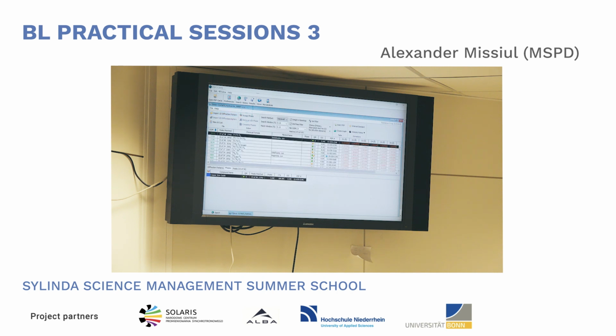So it tries to search. It gives us a list of the possible phases, and for each phase, it gives the figure of merit that tells us how good it corresponds to the experimental data. We go from top to bottom, so we start with the first one, which is really the phase that we wanted to get, the copper iron oxide. So we accept this phase.